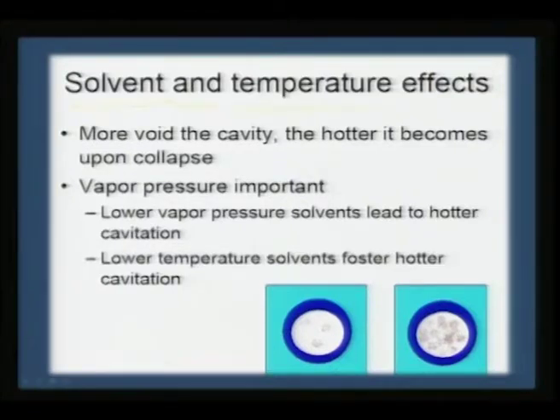So if you look at the solvent and temperature effects, the more void the cavity, the hotter it becomes upon collapse. So if you can trigger a larger cavity, then you can trigger a hotter region and it collapses rapidly. Then vapor pressure of the solvent also becomes important. Lower vapor pressure solvents lead to hotter cavitation, whereas higher vapor pressure solvents do not lead to such hot cavitation. Lower temperature solvents foster hotter cavitations. So these are some thumb rules or guiding principles to realize very high temperatures, which are mainly solvent dependent.